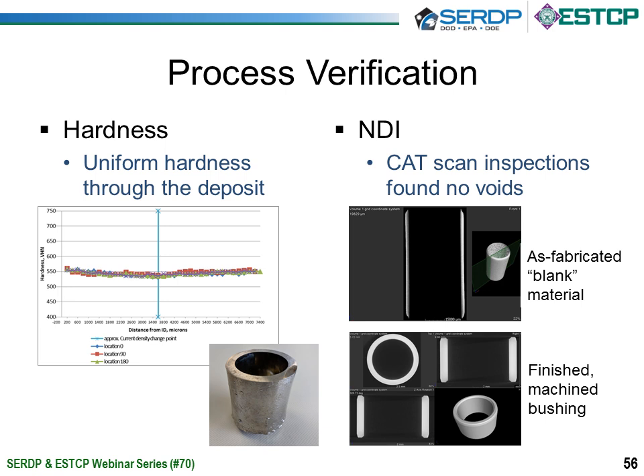In terms of process verification, Vickers micro-hardness has been primarily used to assess the uniformity of the deposit, and through thickness measurements really haven't shown much variation in thickness at all. It's very, very consistent, around 550 Vickers number. The blue line in the plot on the left shows the point at which the current density was changed during the deposition process. And as you can see, it really didn't have much effect on the material hardness.